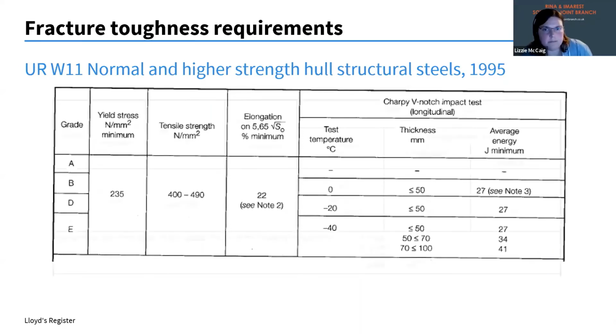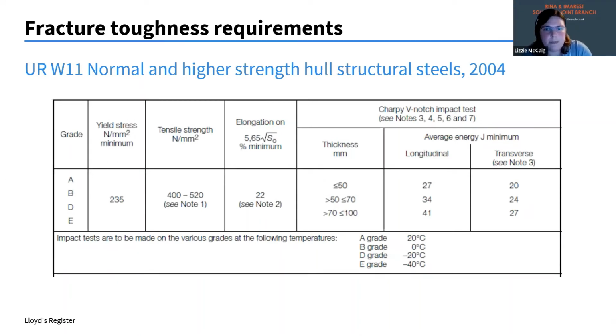And then 2004 is when we see pretty much what we've got now for these standard grades. So grade A is now covered, but it's important to note that now we're relating the thickness to the average energy for the test and looking at both longitudinal and transverse directions. And we also have even lower temperature requirements as you go up from grade A to grade E.